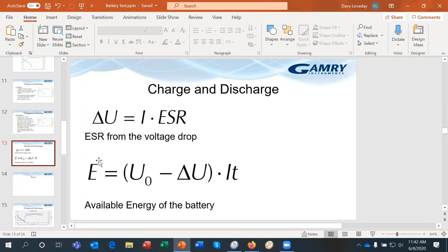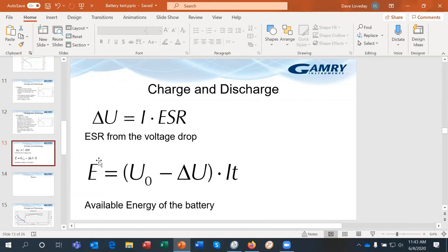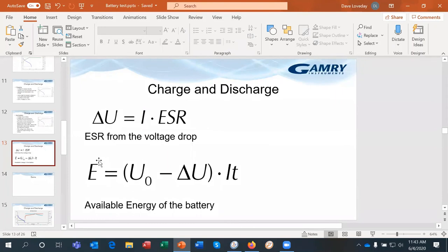Okay, I have a question here, how is ESR calculated? So it's calculated from Ohm's law. If you look at where is it here this is basically a representation of Ohm's law so this is V equals IR so R is V divided by I. So this V is the voltage drop that you get when you first apply the current. So if you charge your battery to 4.2 volts, that initial drop that you see, the first measured point would give you that voltage drop and then you know the current that you applied because it's a constant current experiment so that's the calculation.